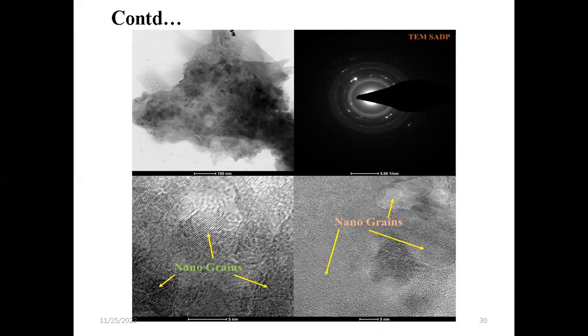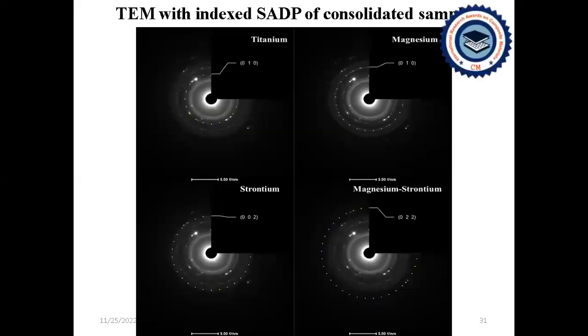Normally grain growth occurs, but since we sintered the sample at low temperature, we were able to retain the nanostructure even after the sintering process. That is indicated by the nano grains in the TEM characterization analysis of the compact sample.